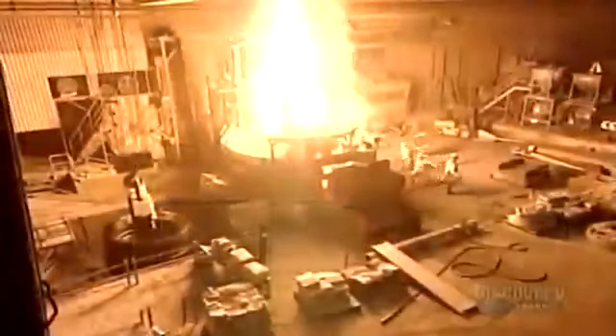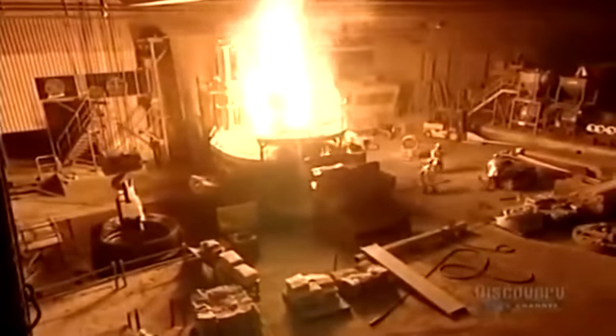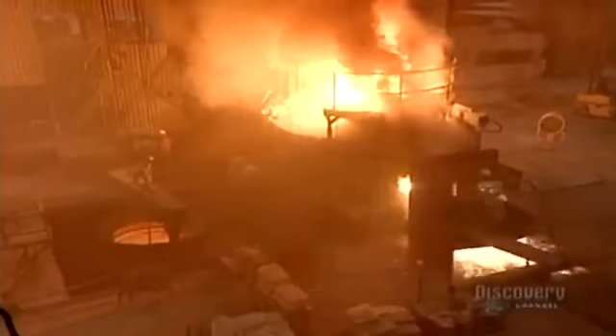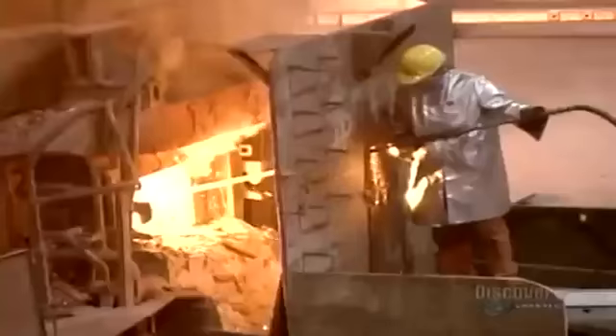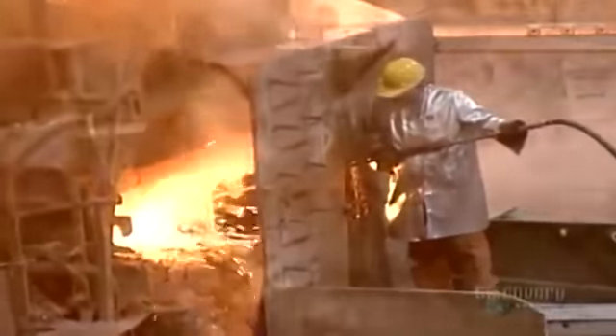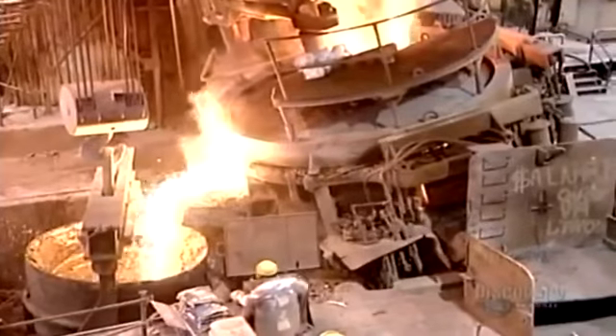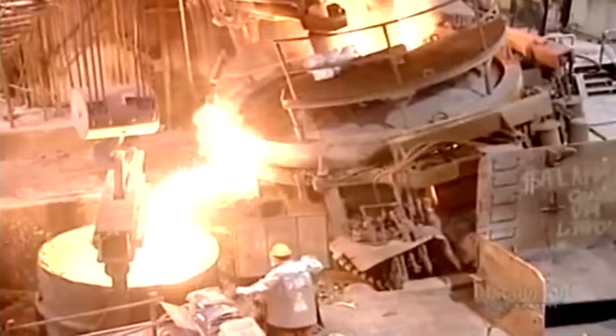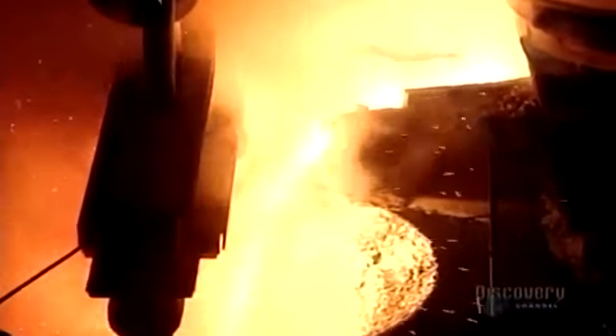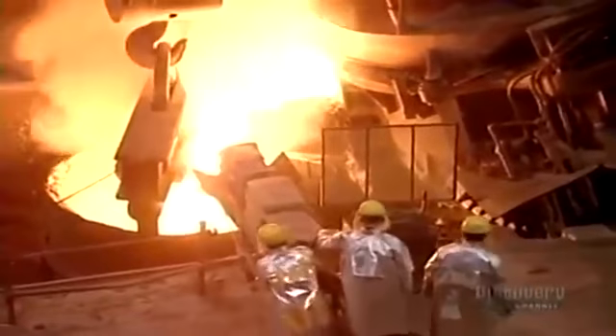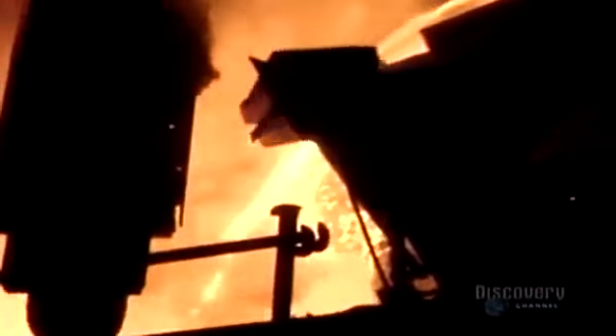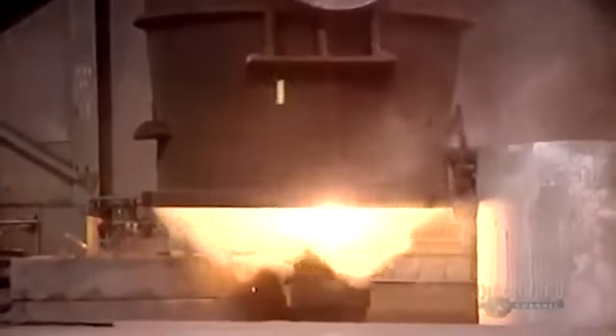Throughout the 3.5-hour meltdown, they test and adjust the chemical composition. They try to attain the lowest hydrogen, oxygen, nitrogen, and sulfur levels, the key to producing strong, high-quality steel. Then they pour the sizzling molten metal into a 45-ton ladle that's lined with heat-resistant brick. They add aluminum and lime to chemically counteract oxidization, rusting caused by air exposure.